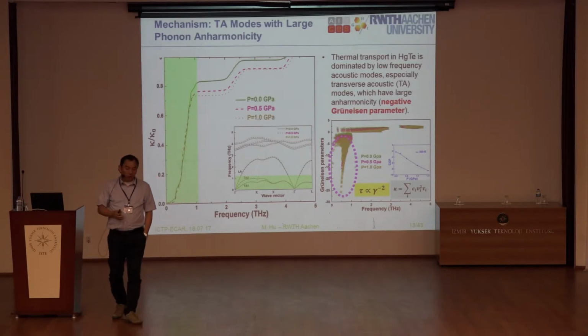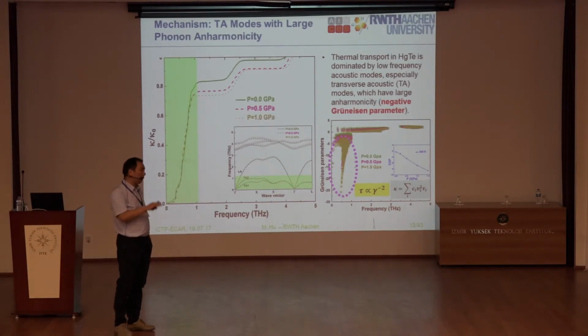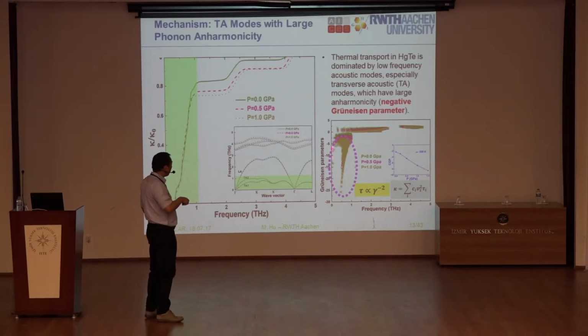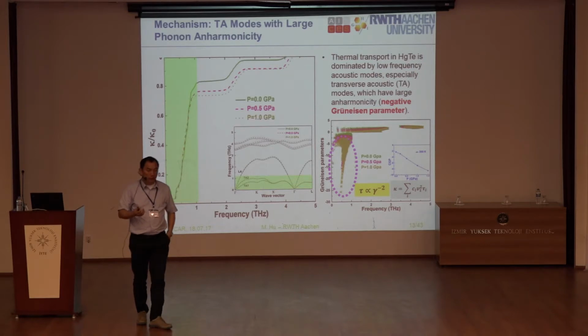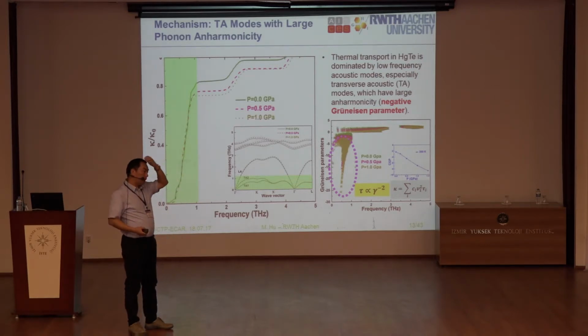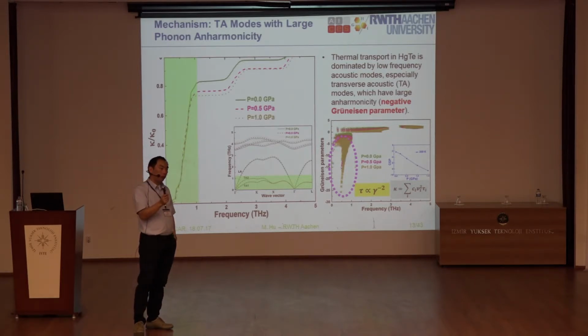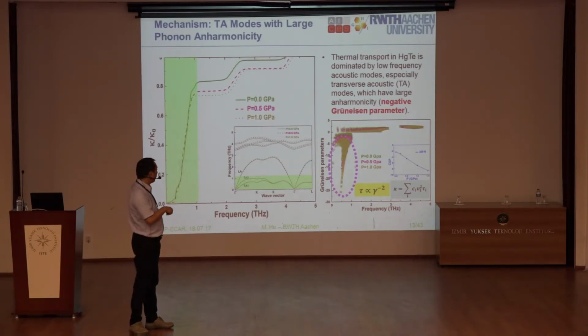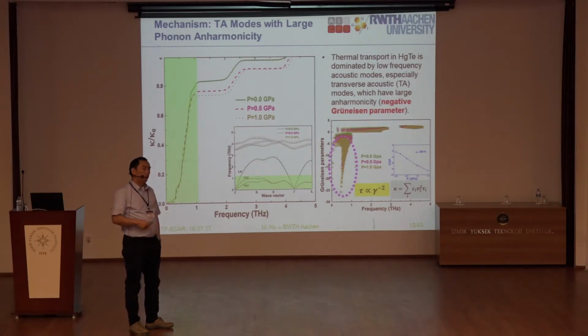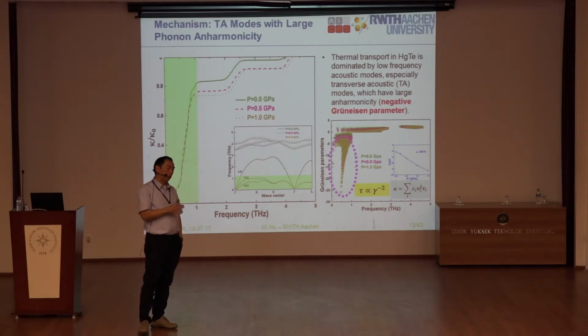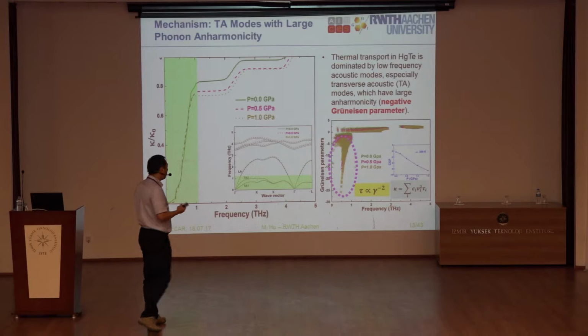Of course, right now we don't know the fundamental reason, because you have to take a look at the electronic structure and how the bonding is so special. But right now we only identify that the TA modes are so special, and we also looked at some literature. Lots of literature said that for negative thermal expansion materials, the TA modes are dominant. It's very rare to find this with the LA modes, the longitudinal acoustic modes. In most cases they do not have negative thermal expansion or a negative Grüneisen parameter. But the TA modes are so special.